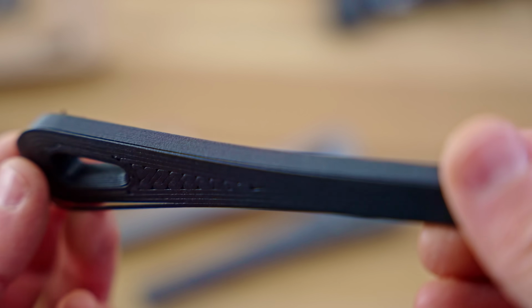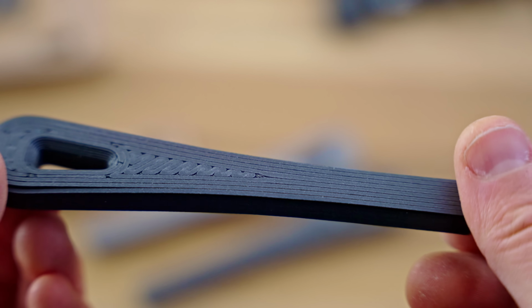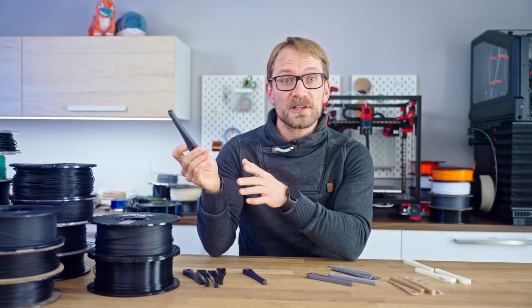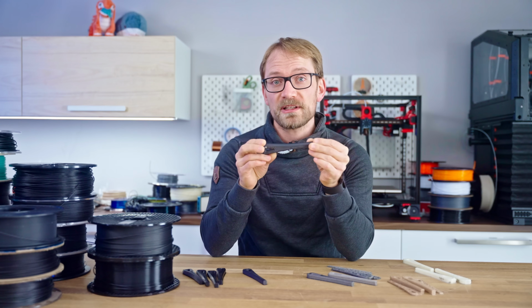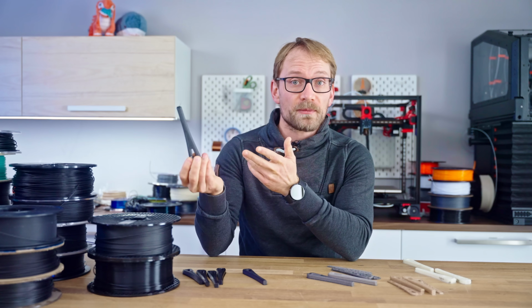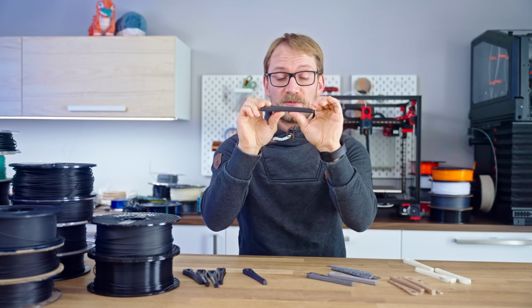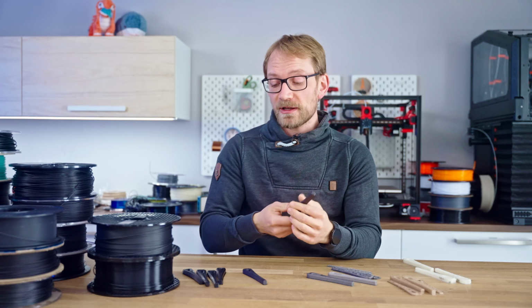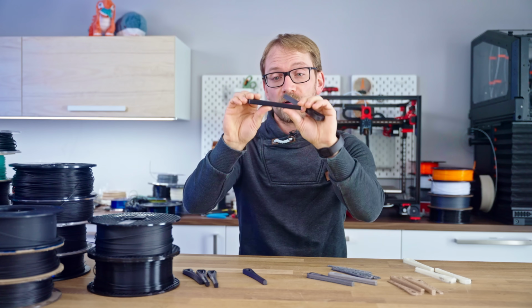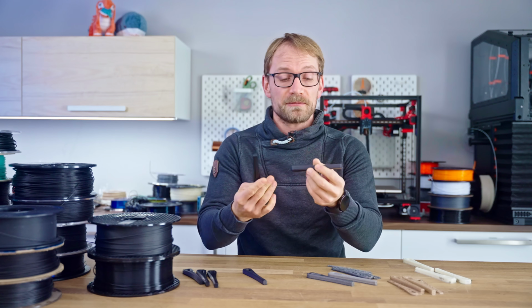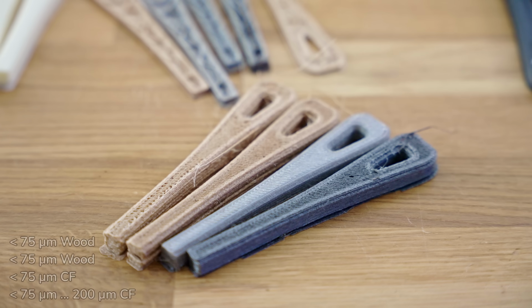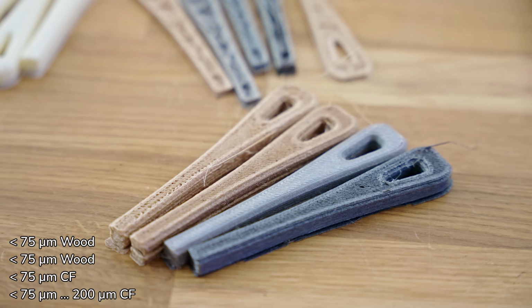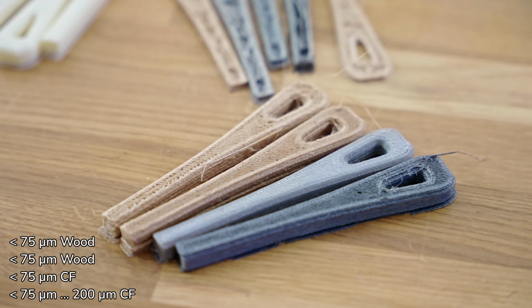I noticed with the Prusa carbon fiber that I used for comparison that it actually became easier to print because the fiber stabilized the part when printing, and it ends up warping less. The finished part is also super rigid. The datasheet claims about a 50 to 100% improvement over pure PC blend, but it feels like a lot more. With my own filament creations, I can't compete with that.